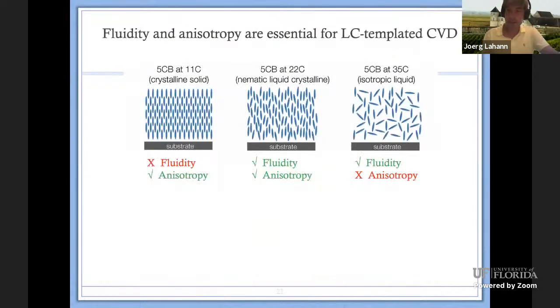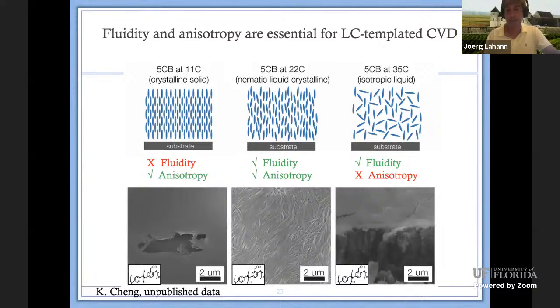So from a mechanistic study, what we learn is when the LC itself is in a crystalline solid form, then we don't get the formation of nanofibers. So we have an anisotropy in the system, but we lack the fluidity. If we go to an isotropic phase, then on the right side we have the fluidity, but we're lacking the long-range order. And in the absence of that, we also don't get nanofibers. Only if both the fluidity and the anisotropy are combined in the form of a nematic liquid crystalline phase, we get the formation of nanofibers. And we have shown this here systematically.